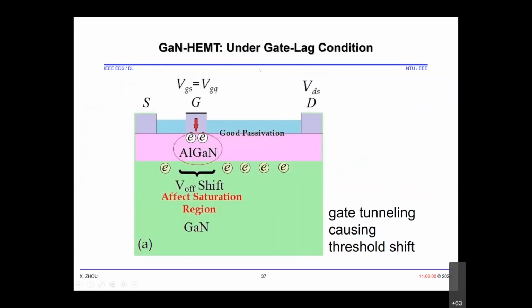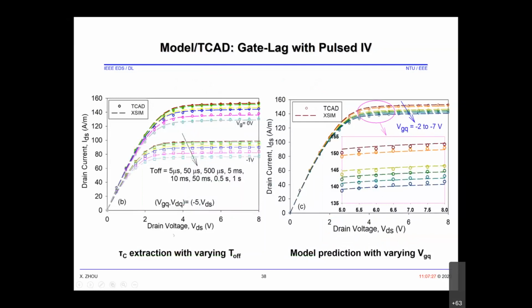Here is the so-called gate lag effect, where traps are generated under the gate, and this will show up as a threshold shift, which affects the saturation region of the device. So here we can see our model. Some model parameters can be extracted by varying the pulse width, and then the model will automatically play back and match the TCAD data. In TCAD, we can specify the exact parameters of the quiescent point and the pulse widths. So our model accurately captures these dependencies.